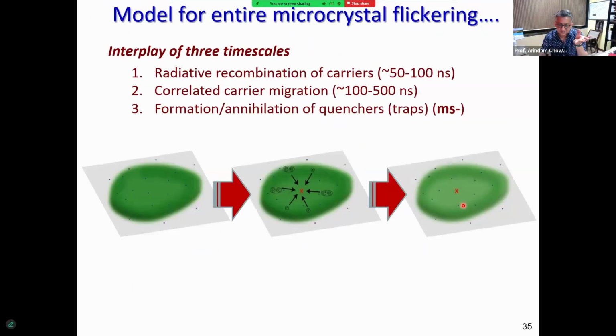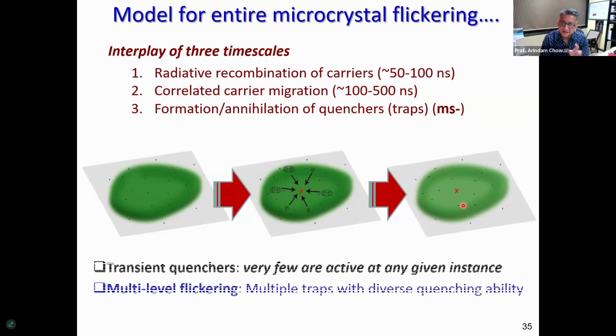So essentially that gives us three different lifetimes or time scales that we're talking about. One is radiative recombination, one is the correlated carrier migration, which we believe is the dominant pathway, but there are other pathways such as waveguide assisted photon recycling that also happen. I don't want to go into the details, but I think the slowest step is the formation and the annihilation of these quenchers or these traps.